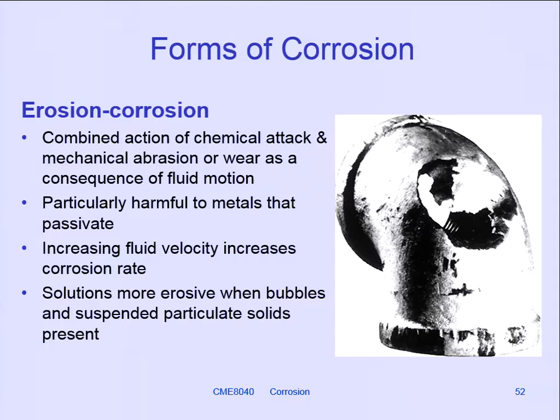In your pipe network, of course, you've got welded joints between two pipes, and we were looking at the root of the weld before. If the root of the weld is sticking out on the inside diameter of the pipe, there's a converse one here.